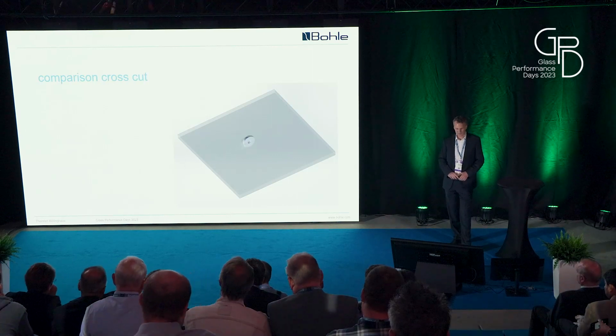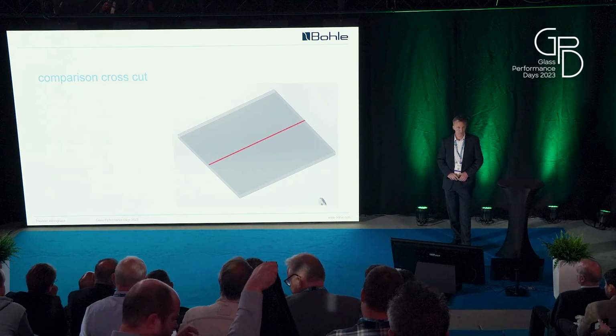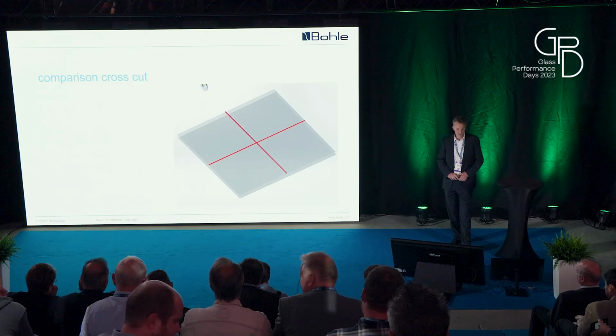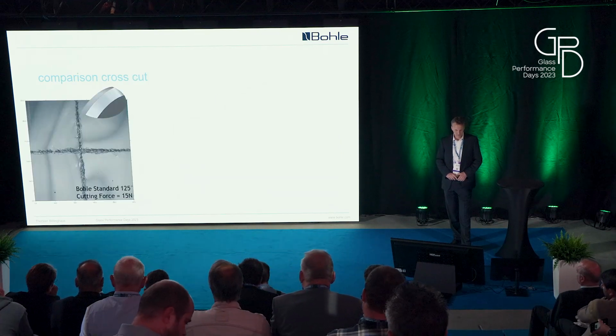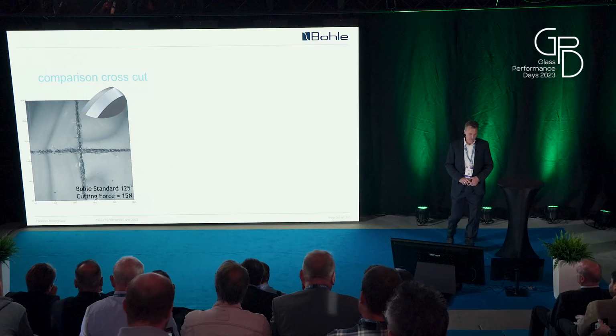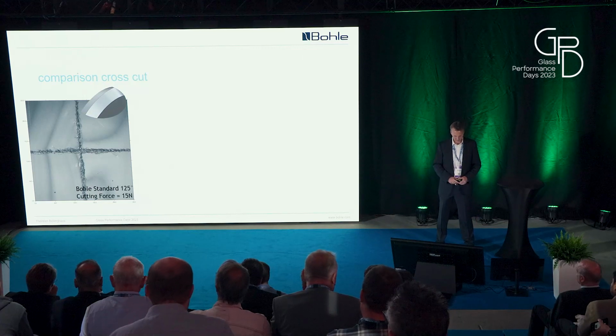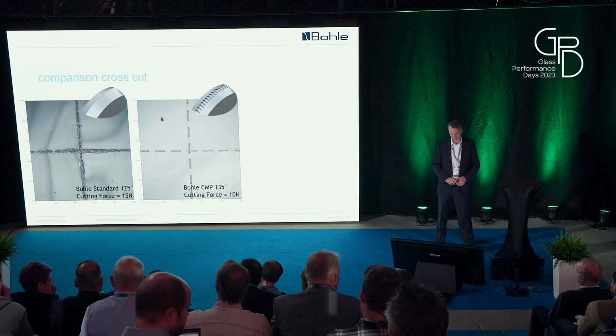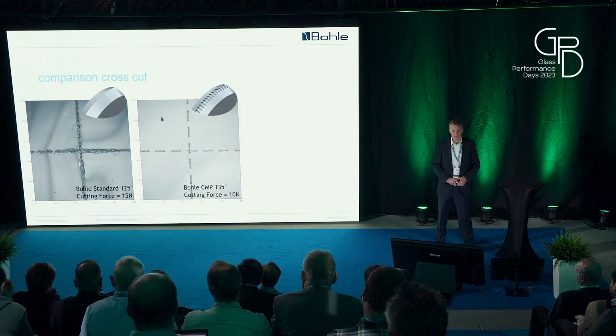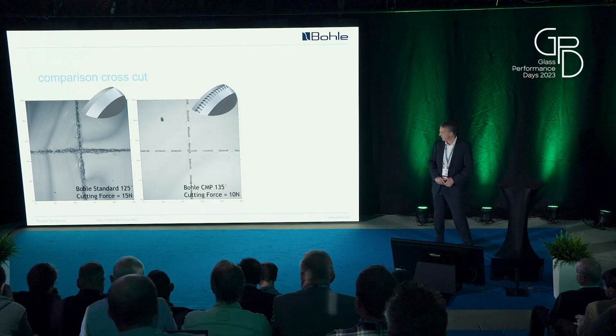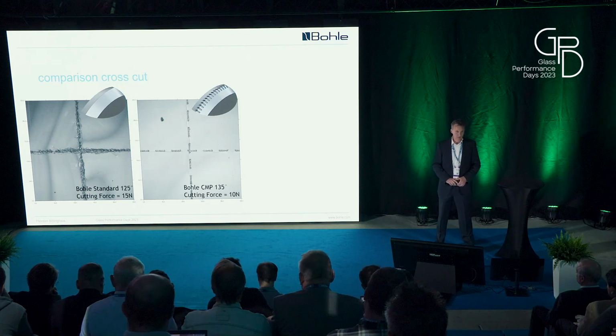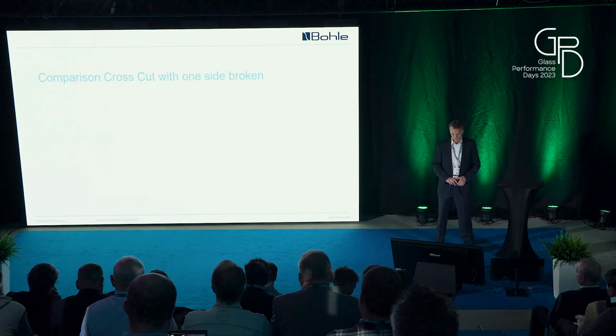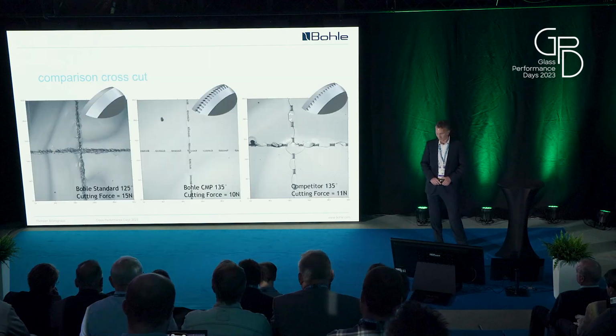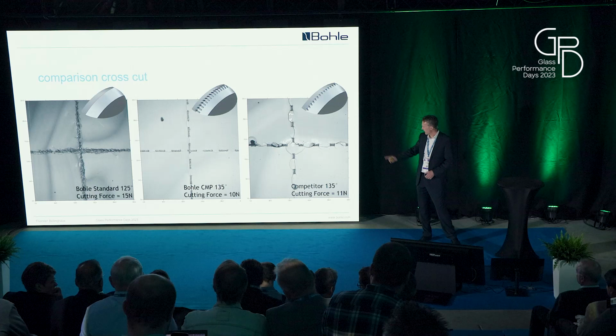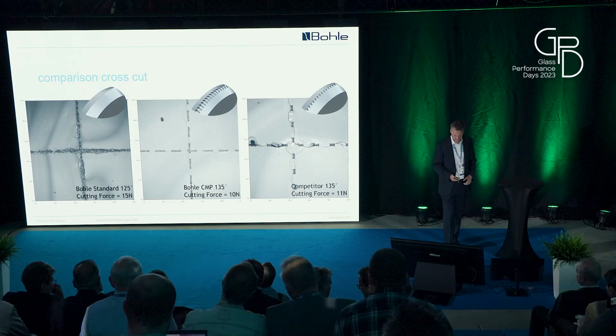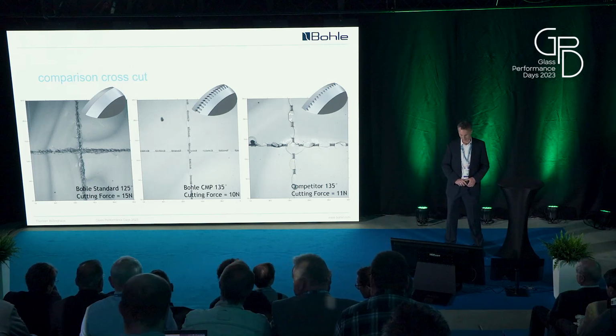So if you now do a cross cut, that's what you do for the evaluation of glass, and look at it from the top, that's what the classical cut looks like, with the side effects and the radial cracks and things like that that come with a normal classical cut. You compare this to the recessed edge microstructured wheel, and you see this perfect image. And also you see that if you don't have the continuous recessed cutting edge, then you get side effects that are almost similar to those of a classical cutting wheel.